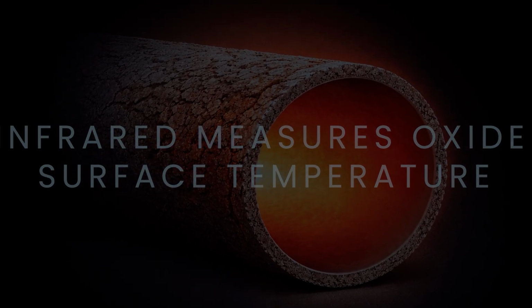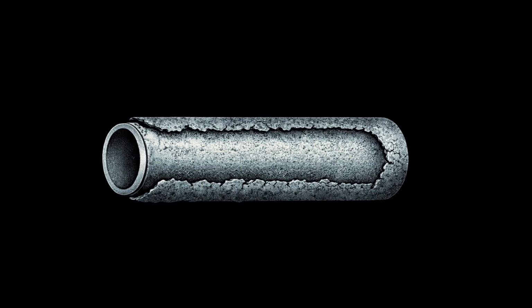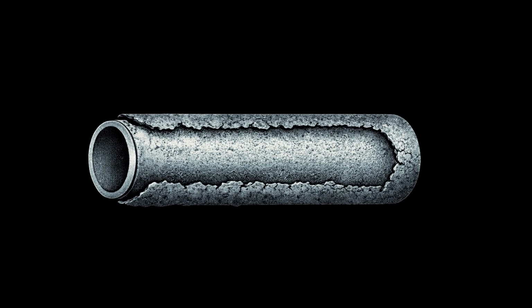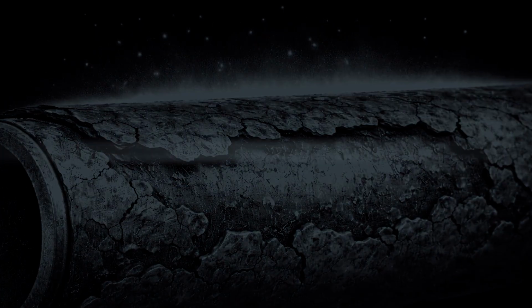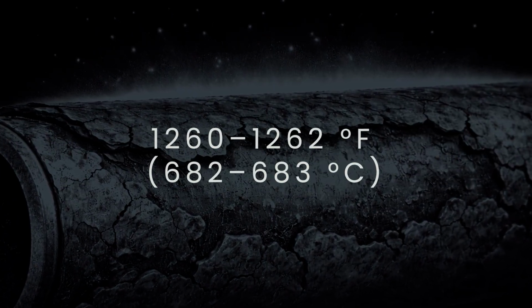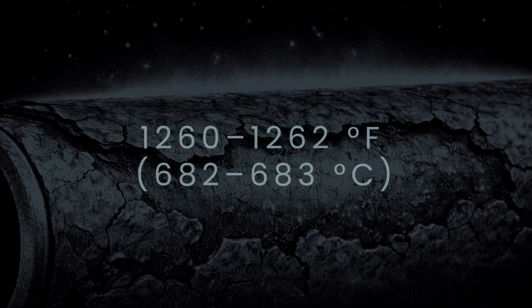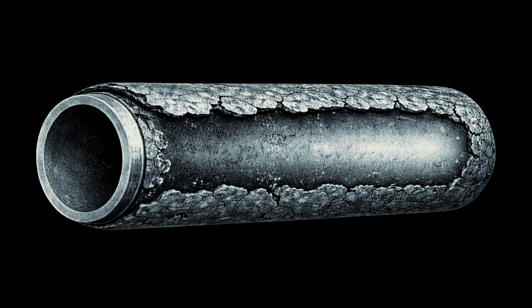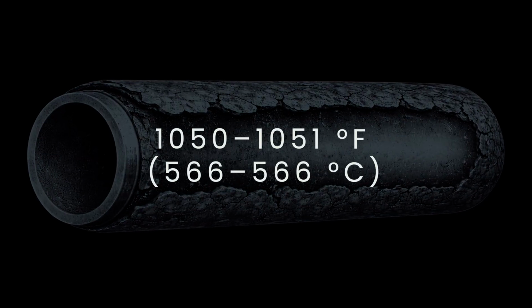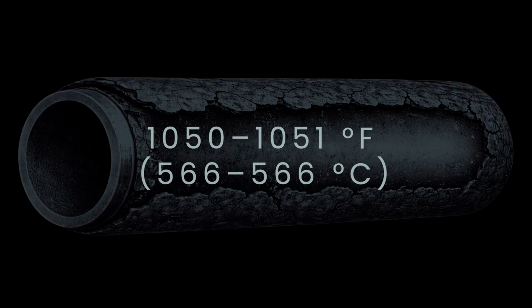In one documented case, we had, let's say, 15 mils of oxide on this tube, and we measured a surface temperature of approximately 1262 Fahrenheit. But the actual metal temperature underneath it, which was measured by the thermocouple, was really only 1050, 1051. That's a difference of over 200 degrees F. And that's caused purely by the insulation effect of the oxide layer.